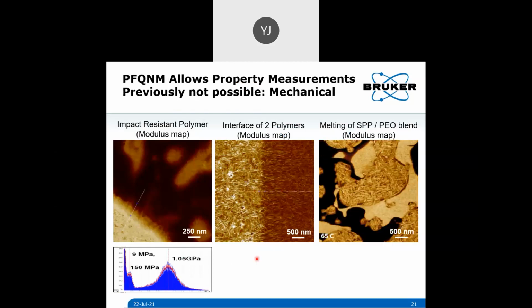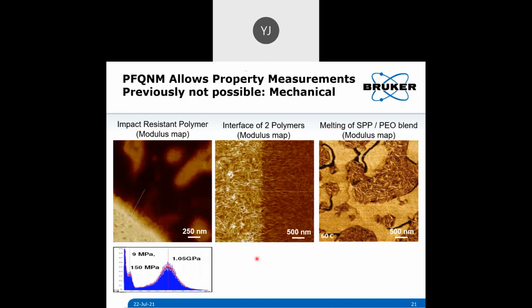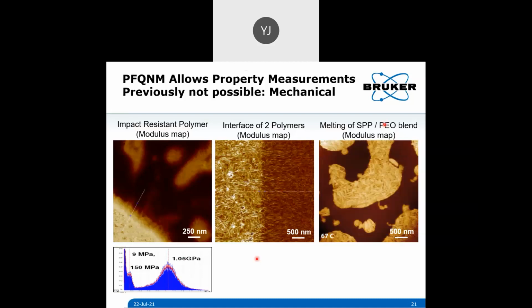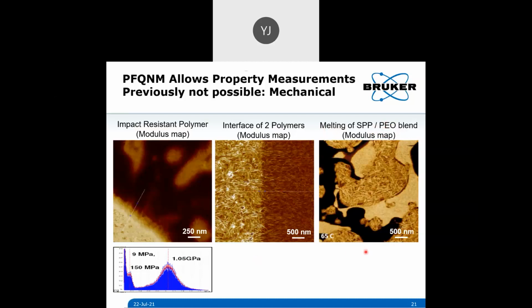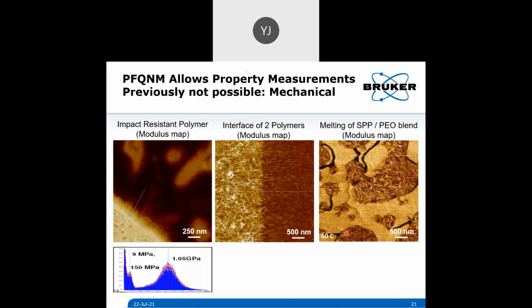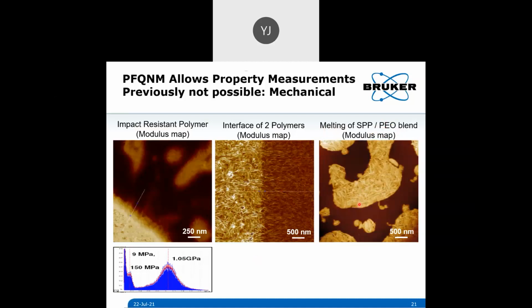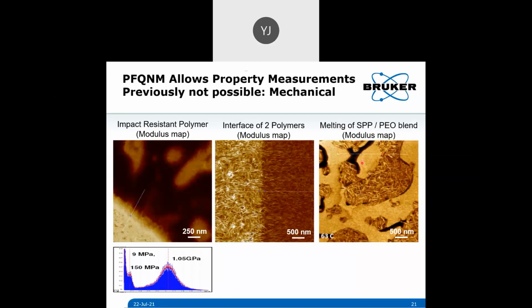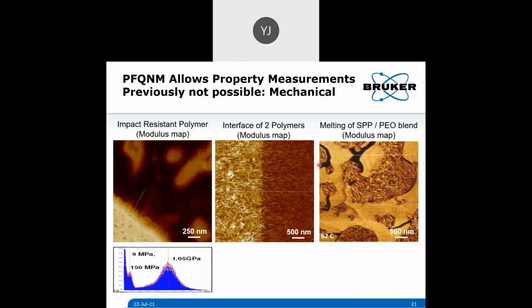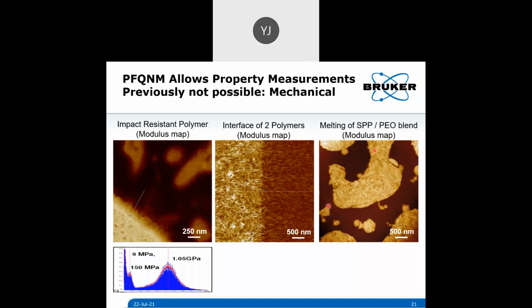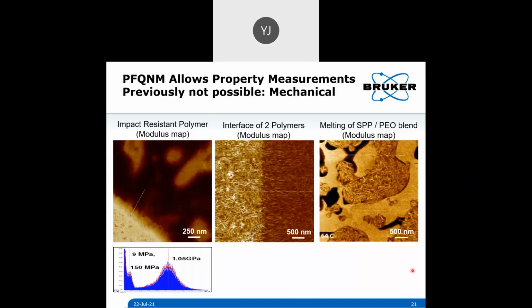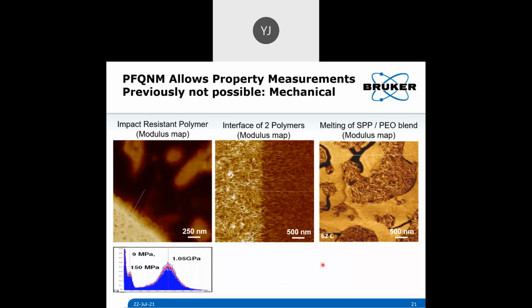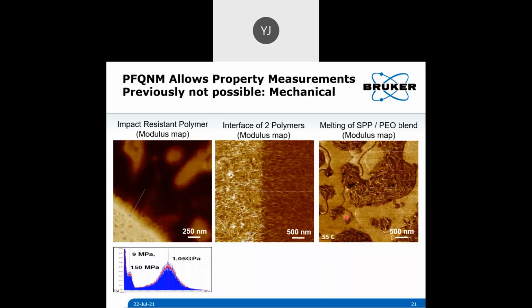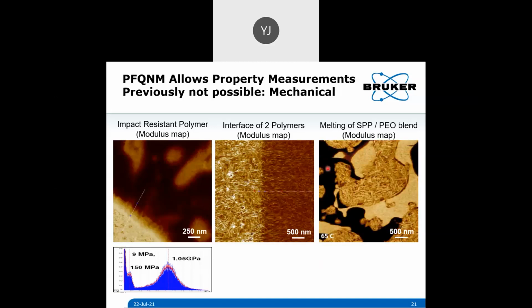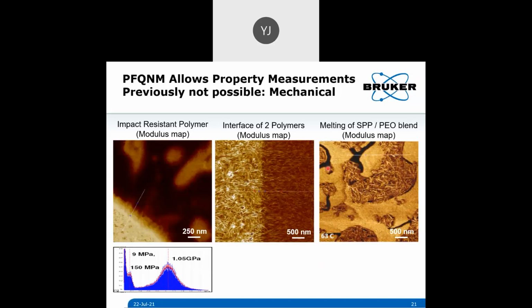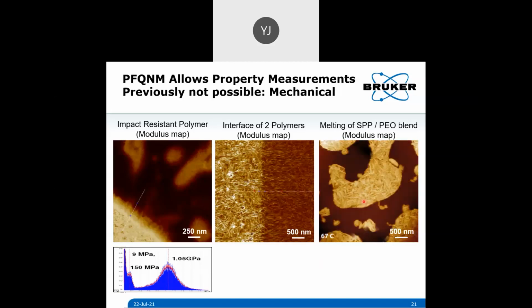And you can also overlay these kind of things with the temperature changes, right? So here you basically have a melting of SPP and PEO, and we are recording images as the temperature is increasing, and you can see the material soften. That's why it becomes a little darker, right? So the harder material soften, and you can see these kind of fibril structures. These don't soften that much, whereas the bulk of the matrix is softening much more rapidly as the temperature is changing. These are very high resolution, so it's about 500 nanometer scale bar, and you can clearly see this. So in the old days, you have no idea what's happening when you heat. Now you can actually point which polymer is softening and where it is going, how the soften process is progressing, etc. Right? So that's the power now.